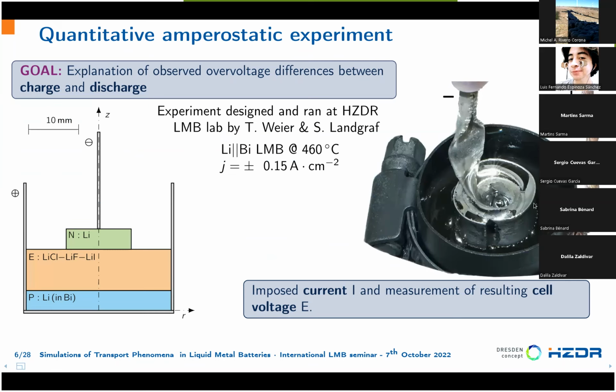And here a photo of the experiment. So on top we see this spiral that contains lithium. Then the transparent fluid that we see here is the molten salt, and below there is the positive electrode that we cannot see. Here are schematics of this cell with the 3 layers. The experiment is run under an amperostatic condition. This means the current is imposed and the cell voltage is measured.